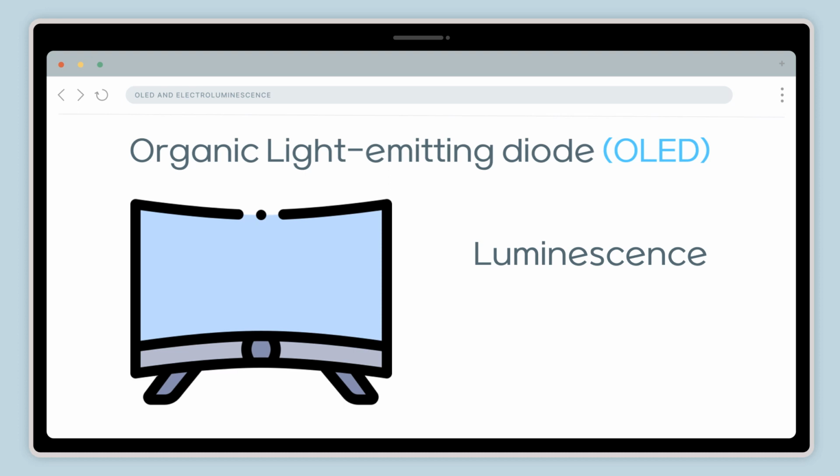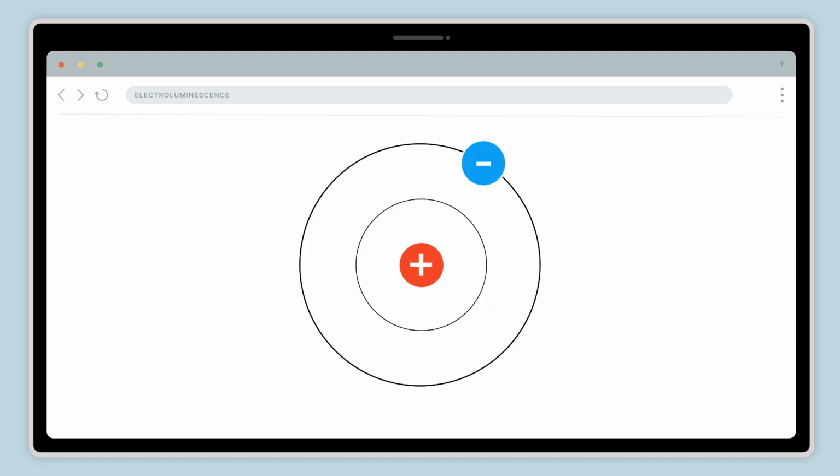The basic principle of emitting light is electroluminescence. Electroluminescence is light emitting by applying electricity to light-emitting materials, especially in organic light-emitting diode, where energy is generated when electrons and holes meet. When an electron in an excited state falls down and meets a hole, the energy of the electron becomes lower and the electron discards its excitation energy as a photon. For releasing energy as photons by electroluminescence, several light-emitting methods called radiative decay processes are used.